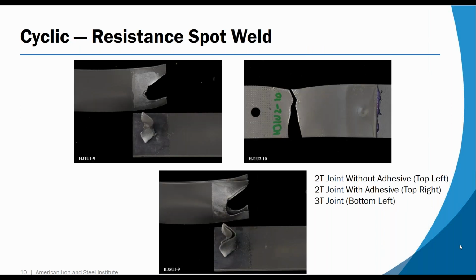These are the same 3 joints, but they're tested in cyclic fatigue instead of quasi-static pull. The failure modes remain essentially the same, but you can see from the shape they exhibit more of a brittle failure behavior, which is typical for cyclic fatigue. So again, we are pulling a nugget on the 2T, we are failing the top sheet on the 2T with adhesive, and we are pulling a nugget on the 3 thickness.